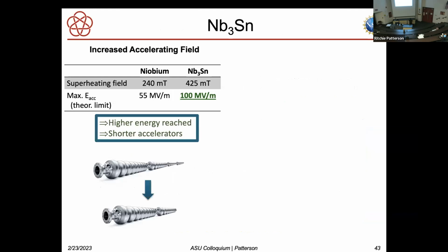So we're trying to think about other materials that could work, alternatives to niobium. And the leading contender is niobium-3 tin. And there are a couple of reasons. One is that it allows potentially for a higher accelerating gradient, a higher accelerating field. And that's because the superheating critical field is higher. So here's niobium, there's niobium-3 tin. The accelerating gradient's proportional to that. And so it's about twice as high in niobium-3 tin as in niobium. And that means you can have a particle accelerator that's half as long.